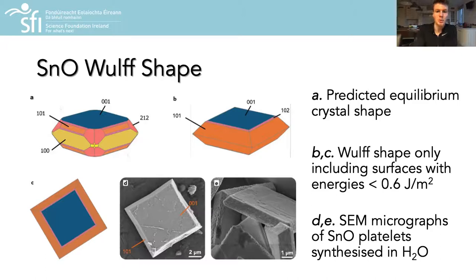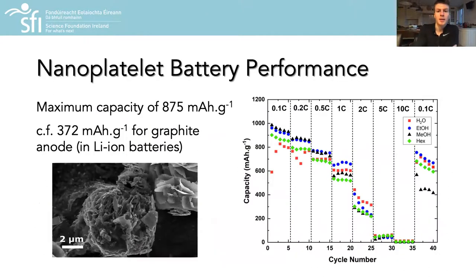Indeed, when we remove the high-energy surfaces from the calculated Wulff shape, the result is a perfect match of the experimental images. Testing these materials as anodes in lithium-ion batteries, we found that they exhibit an enormous charge capacity of close to 900 mAh per gram, compared to under 400 for the commonly and commercially used graphite anode.